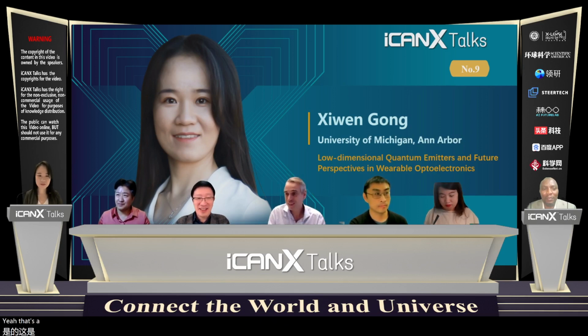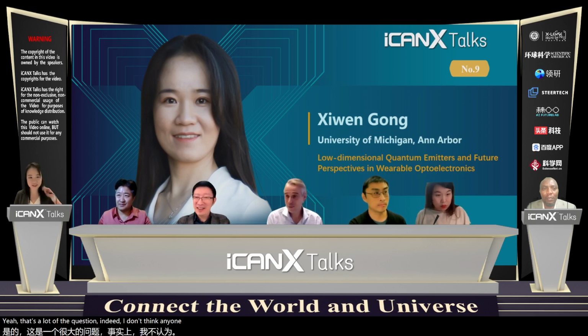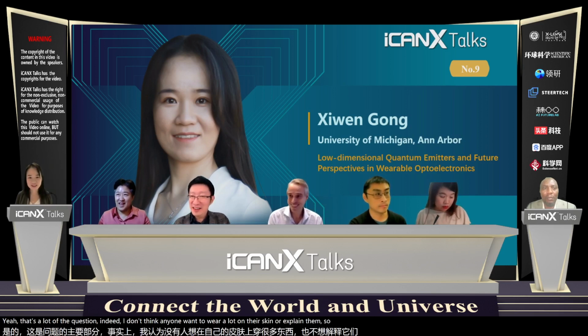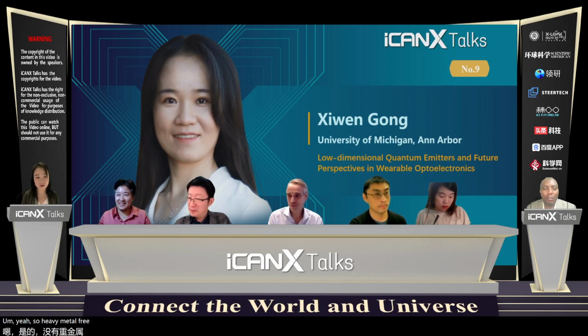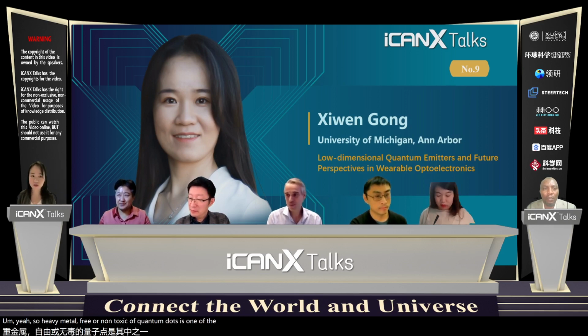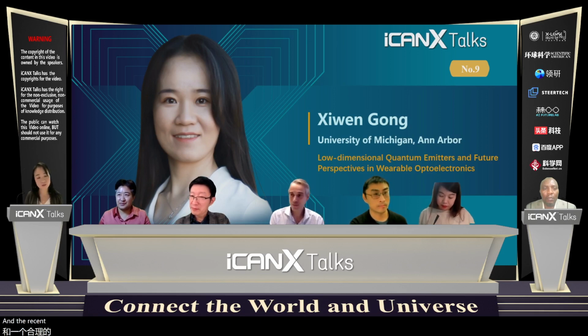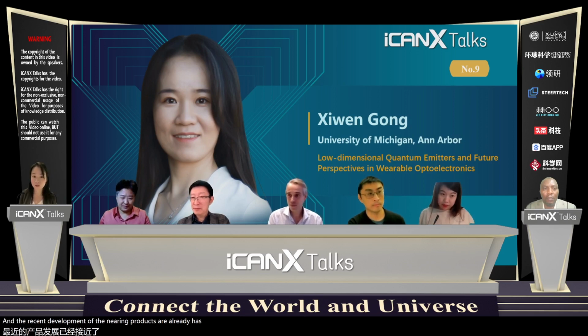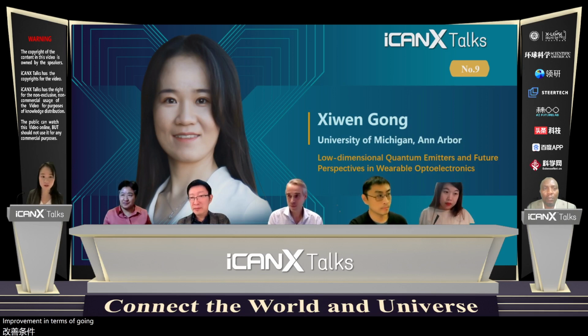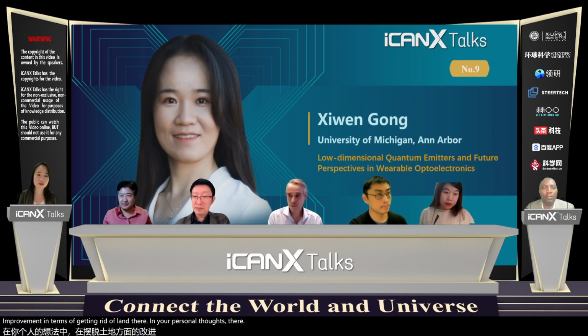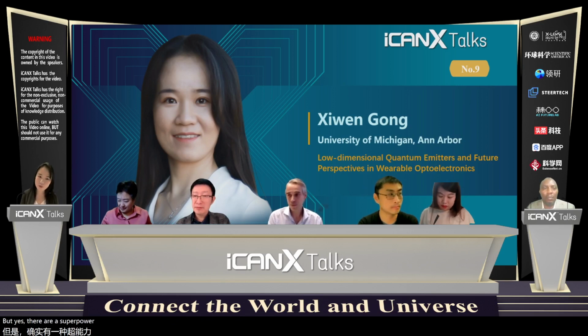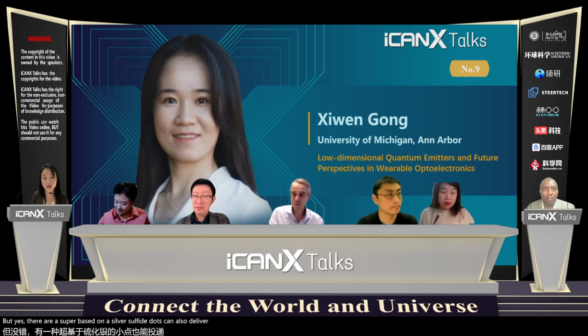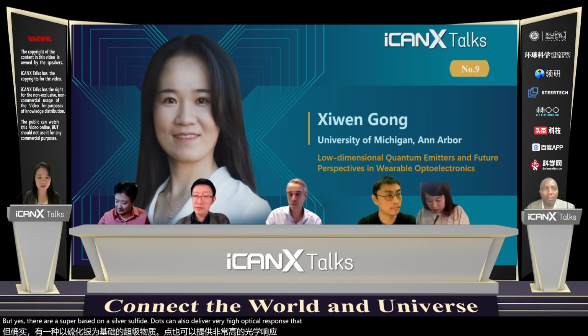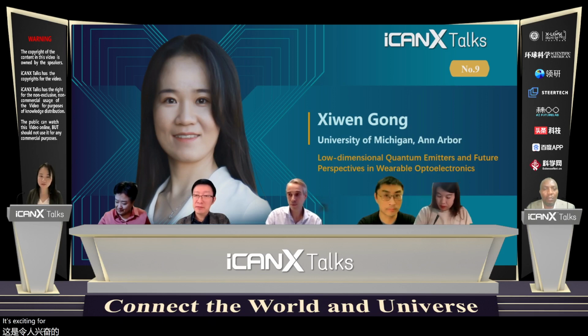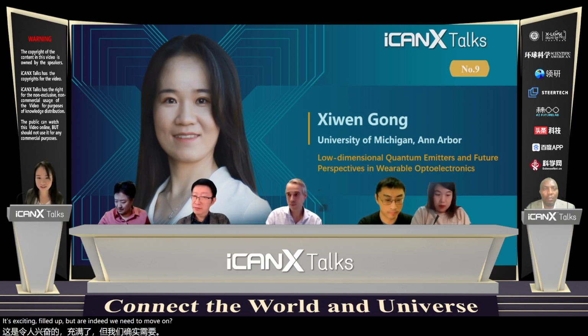Yeah, that's a wonderful question. Indeed, I don't think anyone wants to wear lead on their skin or implant it. So heavy metal free or non-toxic quantum dots is one of the important areas in our research too. And the recent development of the near-infrared dots already has some improvement in terms of getting rid of lead. There are indium arsenide dots. There are, well, mercury, probably not an improvement. But yeah, silver-based, silver sulfide dots can also deliver very high optical response without lead. So it's an exciting field, but indeed we need to move further.